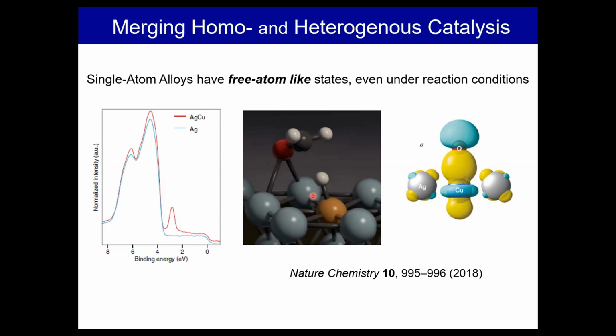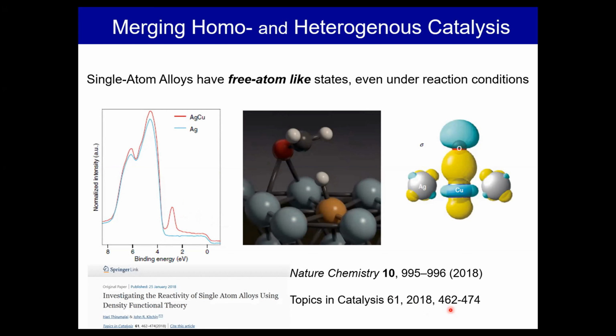So it's because of the lack of hybridization between a lot of these combinations that you get these localized D states, and that's where a lot of the reaction can be centered, and that sort of breaks you away from typical the D-band model and so on. And I'll point you towards a fairly recent paper by John's group that discusses a lot of these computed electronic structures and the effect on reaction barriers.